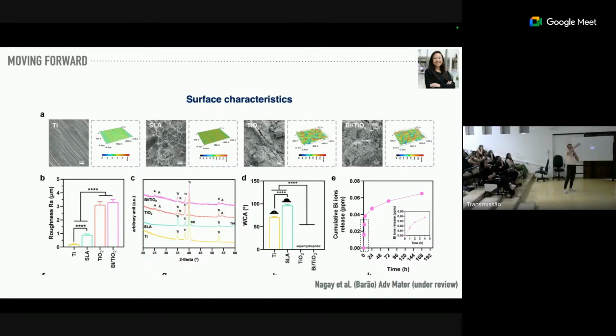It's from my same student, and this is some results of her PhD study. I'm not showing all the results, but some. As you can see here, we call in the literature a pancake structure. I cannot see pancake here. Can you see pancake? No, but the thing here is that we are packing like pancake, but for me it's not pancake. But the description in the literature is pancake, when you have TiO2 by itself and you have bismuth. We incorporate bismuth to reduce this band gap.